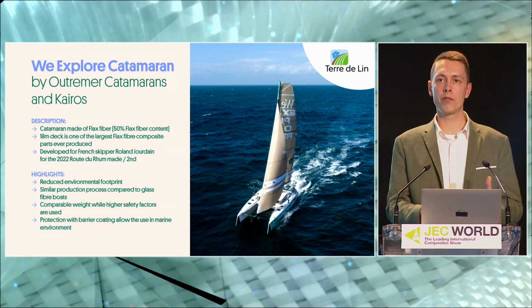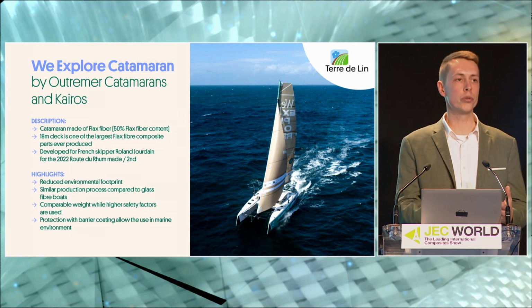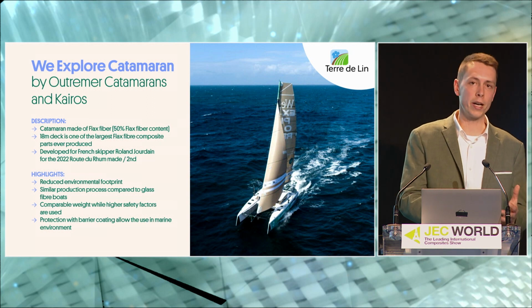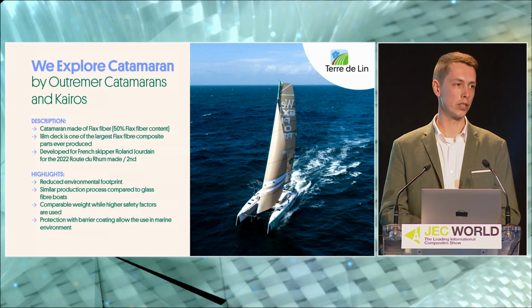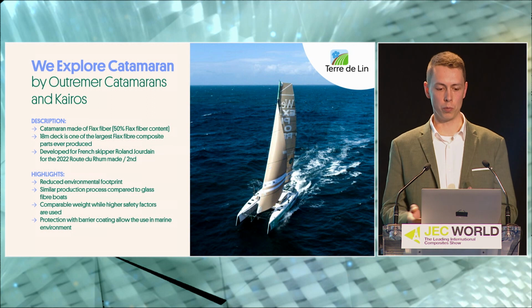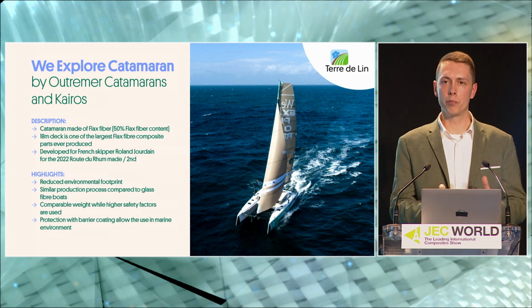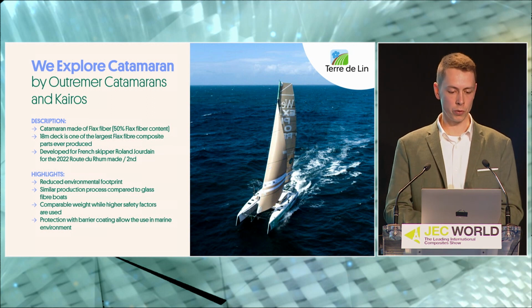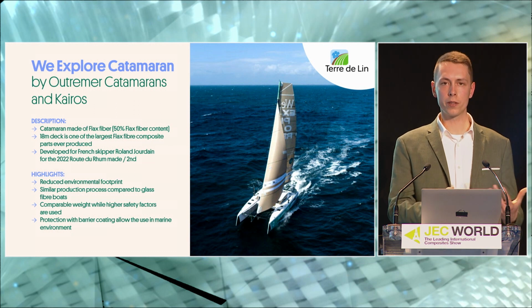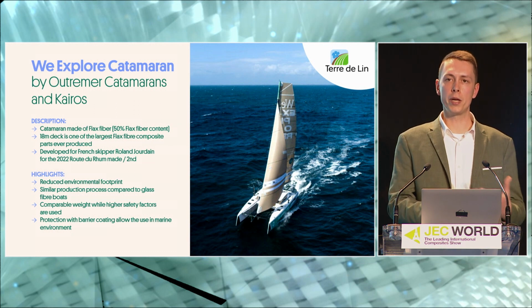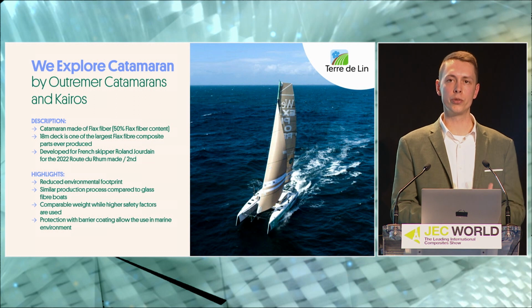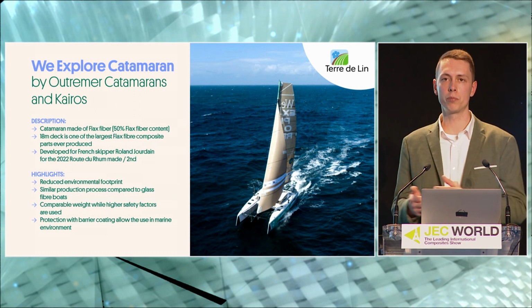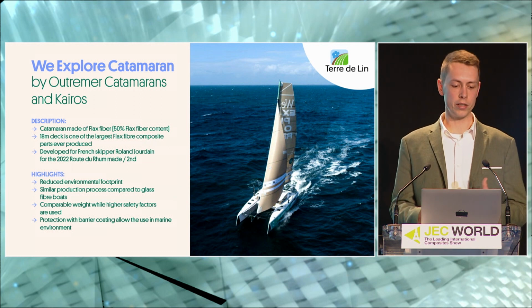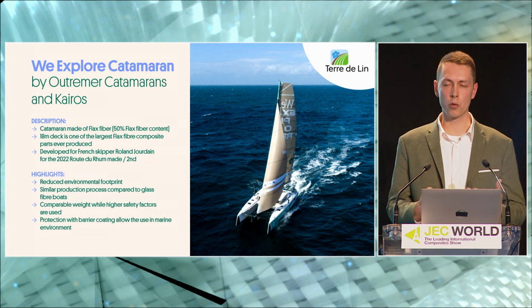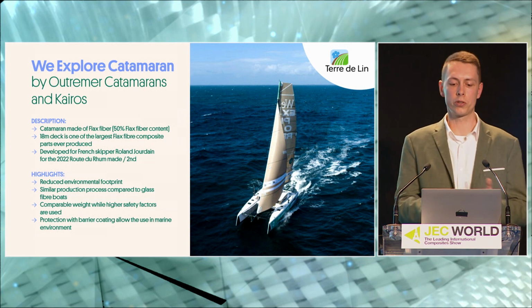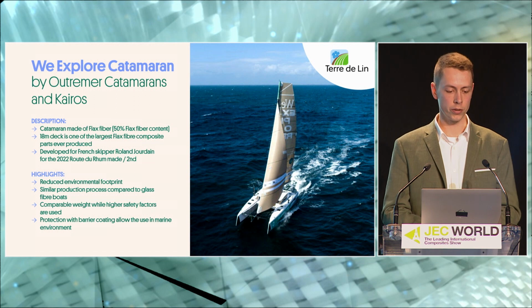And actually, a very similar process can be used with flax fibers compared to glass fiber boats. So the products can be quite easily adaptable. And even if there may be some higher safety factors used for the use of flax fibers in marine environments, still the weight of this product was comparable. So the flax fiber weight was comparable with the glass fiber alternative.